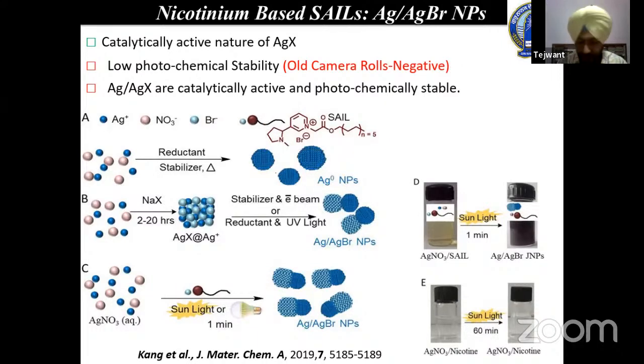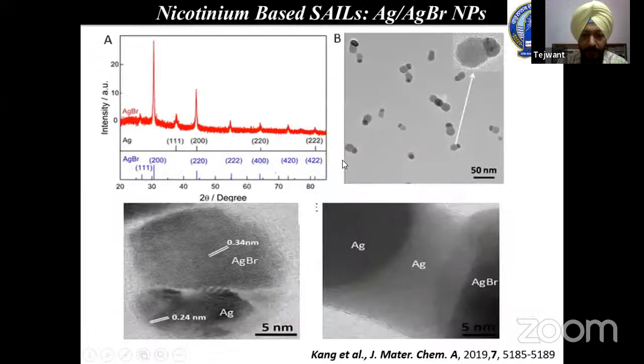Now, for the curiosity of master students, I have included certain figures. The prepared nanoparticles have been characterized by powder XRD pattern. In panel B, you can see the transmission electron microscope image of the prepared Janus nanoparticles. These are dumbbell shaped nanoparticles, and in these nanoparticles, one part has a lower contrast as compared to the other one.